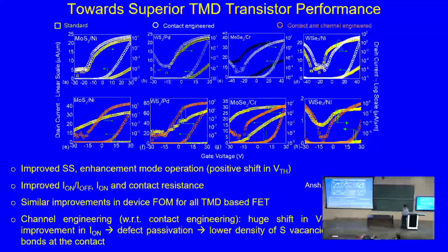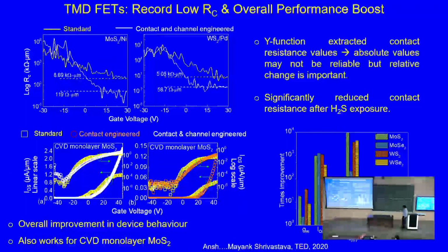So this was graphene. Now let's talk about TMD. I told you how we introduced those sulfur interstitials in the contact area and then metal on top of that. Now these are very stable contacts. Do whatever you want to do on top of that, they will behave as permanent. Now here you see the improvements because of the contact engineering. So this summarizes everything. You see the times improvement in the transconductance, off current, where improvement in off current means the drop in the off current, on current, Ion by Ioff, mobility, subthreshold slope, and contact resistance.